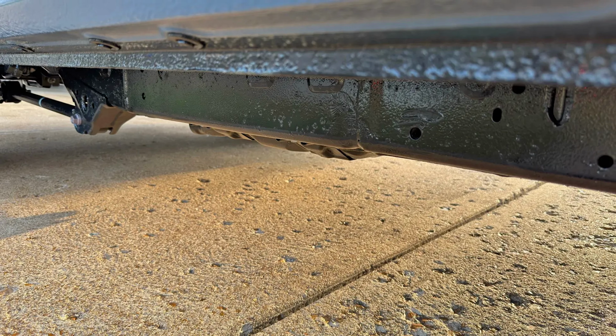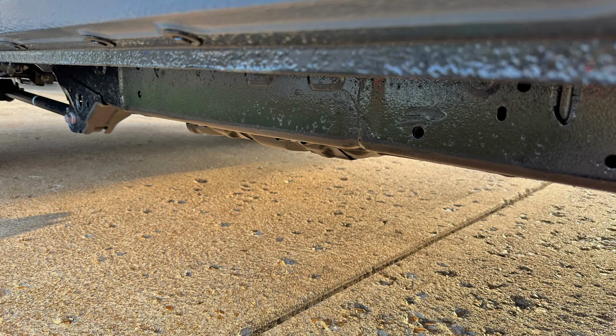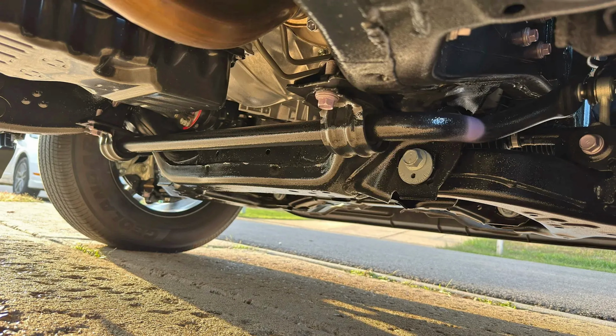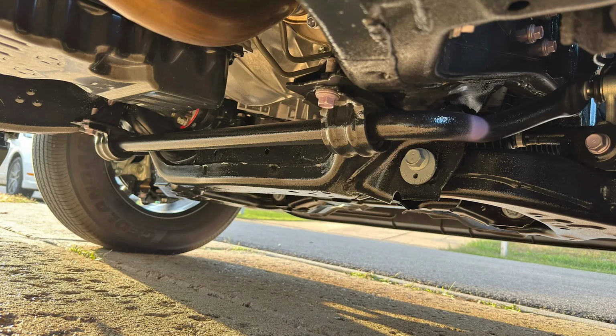For the pros, they do have a level of self-healing and movement. If a rock chips the coating, the oil does migrate over the scratch because it doesn't really dry, it's always a little bit runny. And because they are applied so thick, they do give good corrosion protection, especially when they seep into areas that other products can't reach. The cons, they're messy, they attract sand and mud, and they are limited in their resistance against solvents and chemicals.